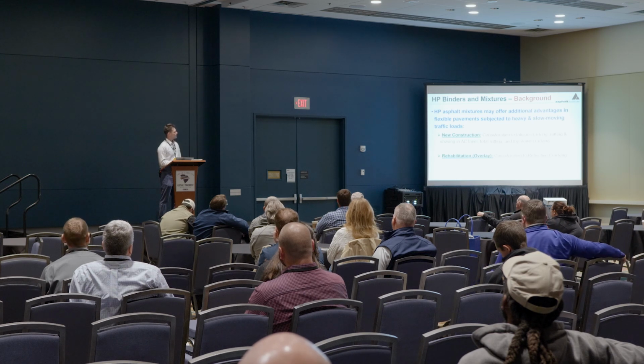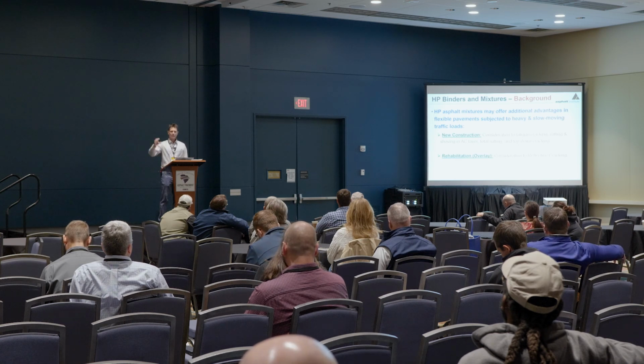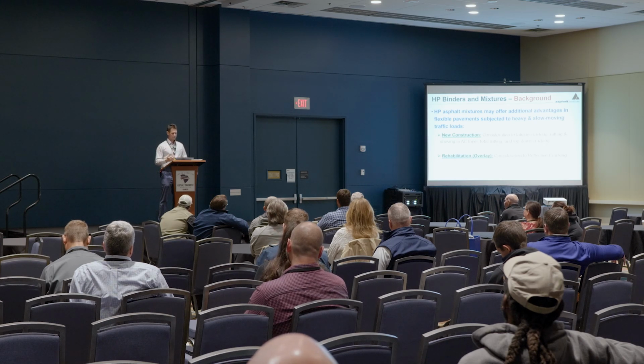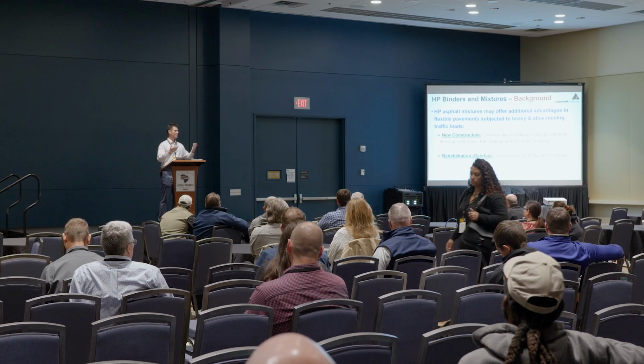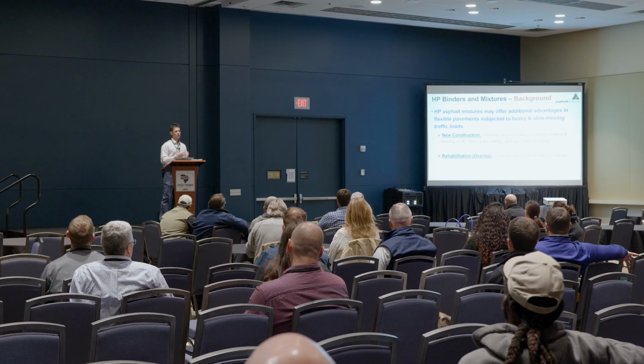So the primary application for high polymer is, of course, to resist those load-related distresses: fatigue cracking and rutting. There's rutting that can happen in the surface, but there's also rutting that can happen in the base layer, okay? High polymer is effective at addressing both types of rutting. It also addresses top-down cracking, and it's really found a home addressing reflective cracking, okay, from PCC pavements and also cracked asphalt pavements, before those cracks reflect through that new surface and imprint onto the new surface.